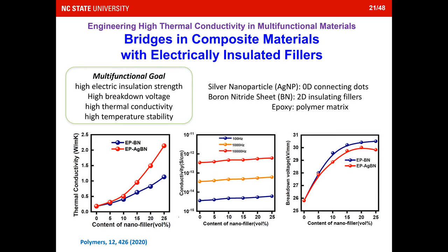What we found through measurement is that the thermal conductivity actually increases a lot with the content of these nanofillers. When you have those nanoparticles, you could have even higher enhancement in thermal conductivity. In terms of electrical conductivity, it still remains at a very low level at different frequencies. The breakdown voltage is actually all pretty high compared to without any of the nanofillers.